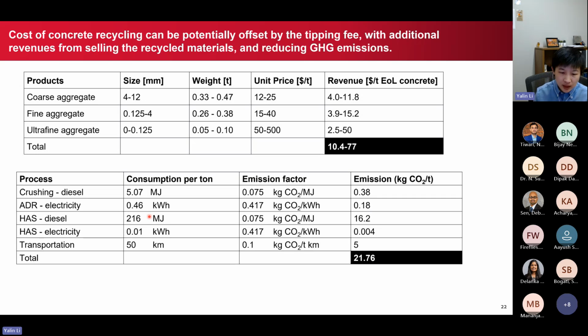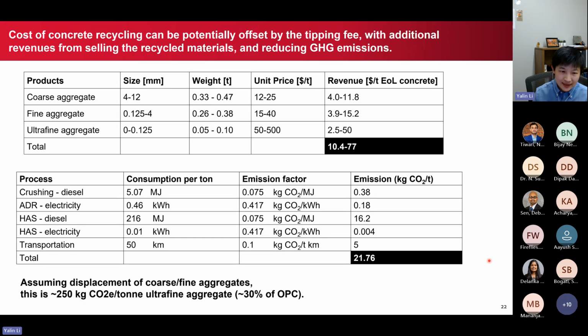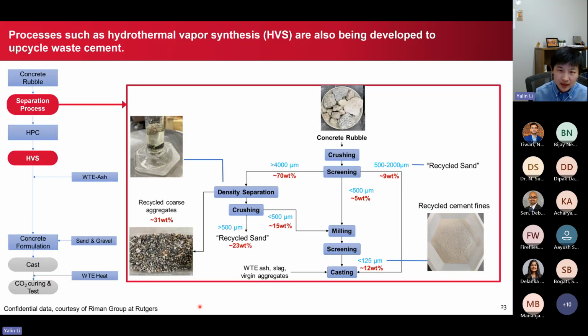And we also did some calculations related to the greenhouse gas emissions of this process. If we use the displacement method for the coarse and fine aggregates, what we get is that the production of the ultra fine aggregates, which we think can be used as either filler materials or to replace the cement, has emissions of around 250 kilograms carbon dioxide per ton, and compared to that from ordinary Portland cement, this is only 30% of the emissions. So by recycling this material, it can also greatly reduce the greenhouse gas emissions associated with that. So this is one technology looking at the recycling of the waste concrete. At Rutgers, we have also worked with researchers from material science and civil engineering on looking at other different processes.